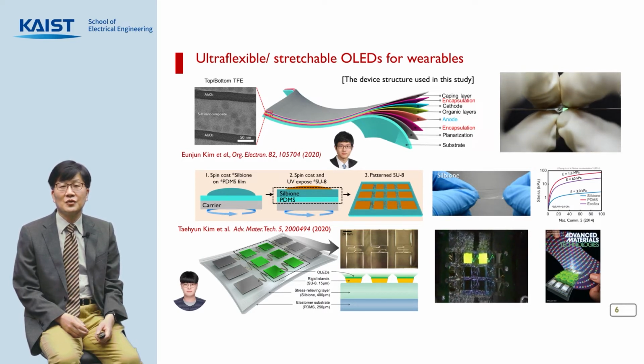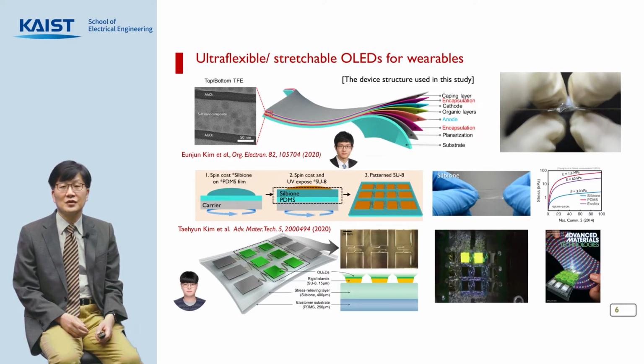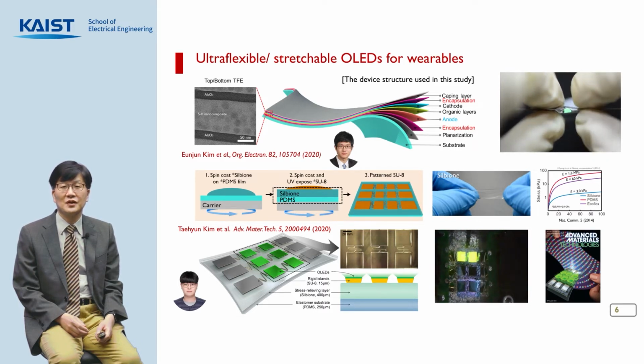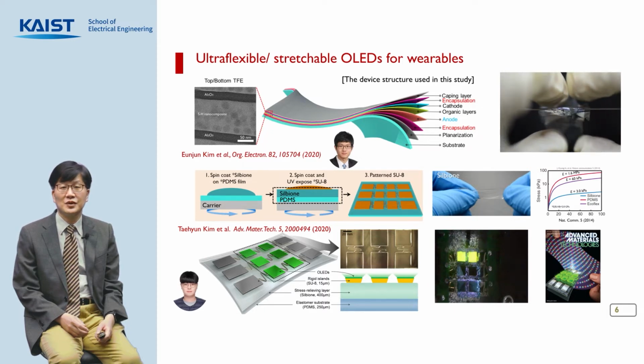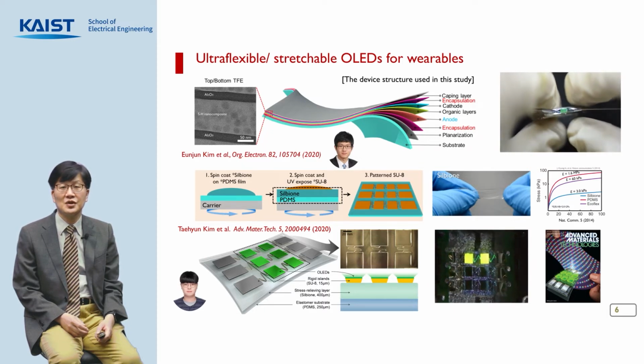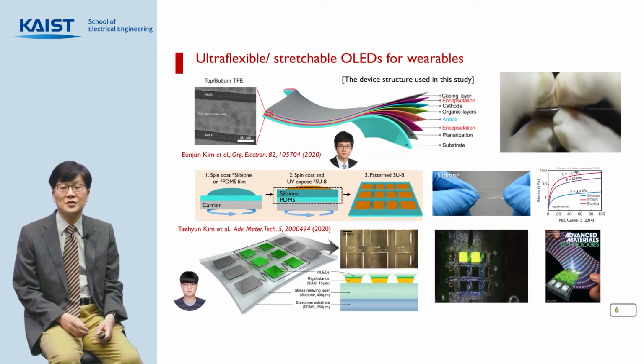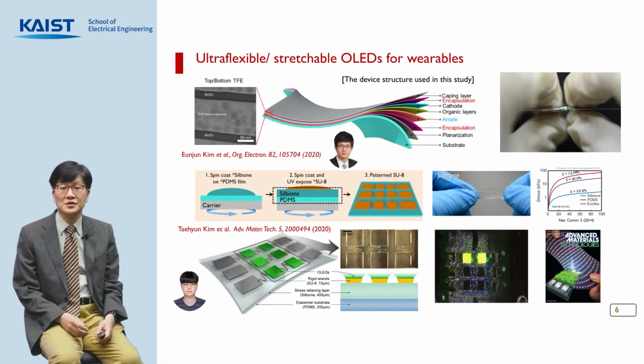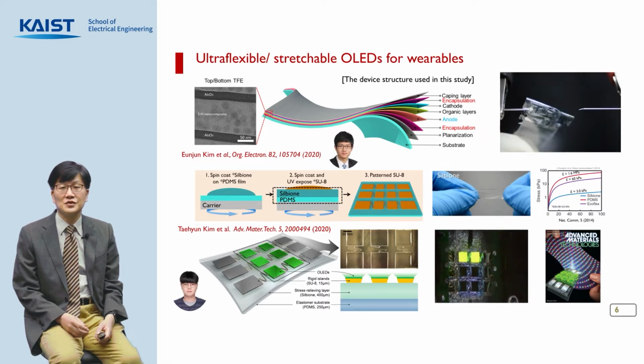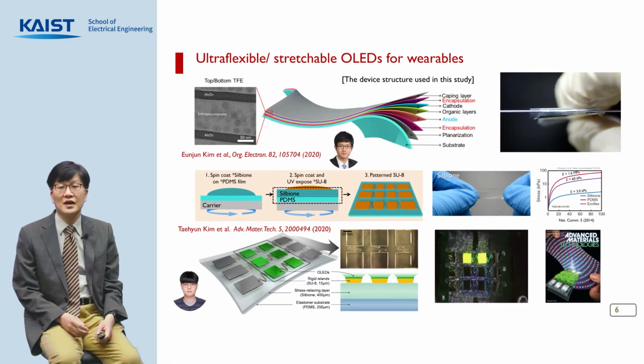This is an example of the work we did for the realization of ultra-flexible OLEDs. Based on 6-micron thick ultra-thin substrates and a careful design considering neutral plane shift in systems on such ultra-thin substrates, these OLEDs exhibit high performance and near-foldable flexibility, even with conventional transparent conductors and alumina-based encapsulation, which are known to be prone to bending-induced fractures.